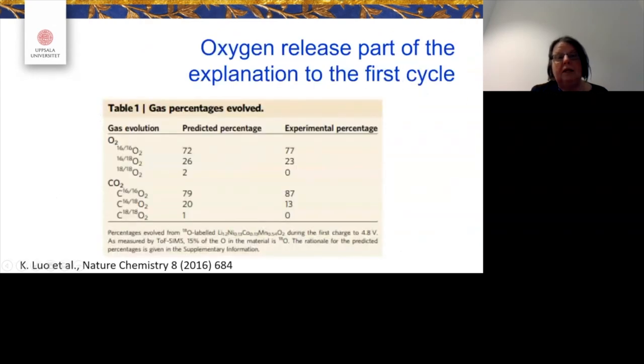And what you can see here is that it's been a big debate about this compound: you have oxygen loss, and the oxygen loss is actually a reason for the capacity fading. In this case, we did some DEMS, differential electrochemical mass spectrometer studies, and could see that, yes, we had predicted gas evolution of oxygen, and we could experimentally verify this. But we can also see carbon dioxide.